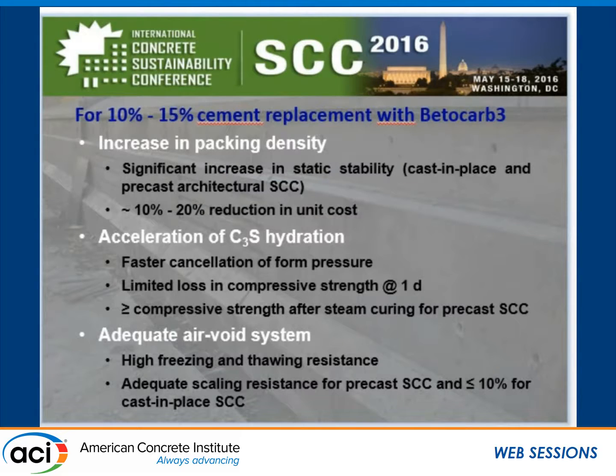In conclusion, if you were to replace 10 to 15% of the cement with finely ground limestone filler, and this is again a D50 of 3 micron, it increases the packing density, which has a significant effect on static stability for all kinds of concretes we tested. It also reduces viscosity and reduces the cost, but the cost is proportional to the reduction of superplasticizer demand. In terms of mechanical properties, we noticed an acceleration of the early hydration of cement, and you notice this by the faster cessation of formwork pressure, but also the shorter dormant period for the tested concretes, limited loss in the one-day strengths, and limited loss at 18 hours after steam curing.